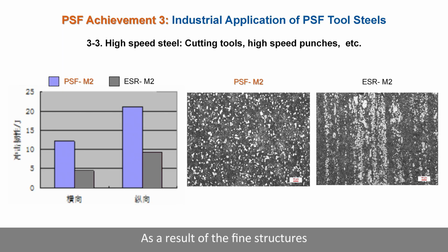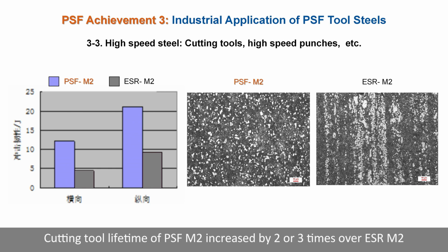As a result of the fine structures, high-speed steel, such as PSF M2, increases impact strength by 100 to 150% at the same hardness, HRC 66. Cutting tool lifetime of PSF M2 increased by 2 or 3 times over ESR M2.